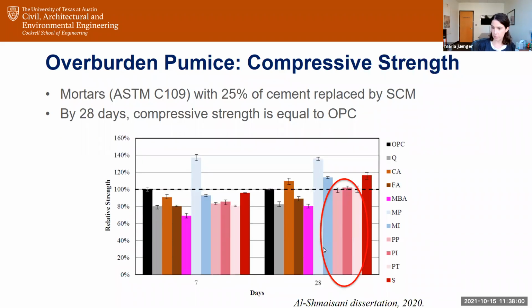In terms of compressive strength, which is another metric people are interested in, these are 28-day strength values. This black one is at 100% relative strength compared to Portland cement, which is in the black. And these materials, this overburden pumice material, has the same compressive strength as a Portland cement. So in terms of being able to replace fly ash with this, be able to make concrete with this, it's a good material. You don't need to use the more pure one.